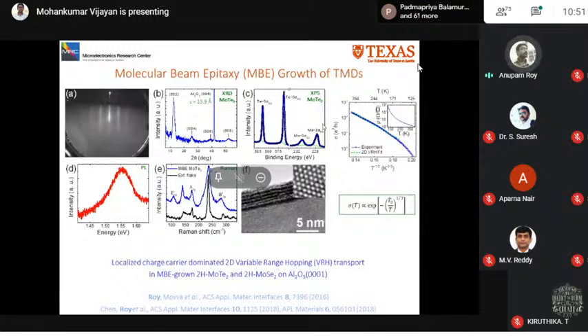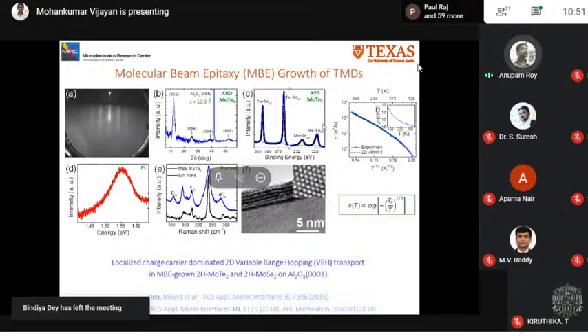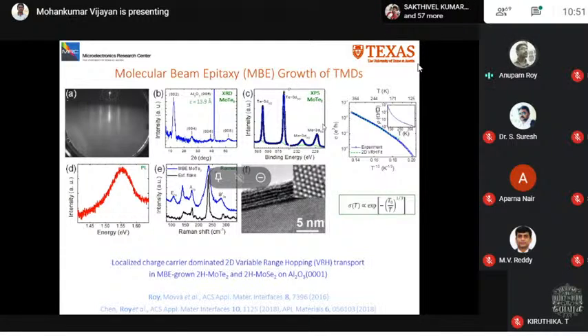And then the characteristic Raman peaks, a band gap of about 1.55 eV in photoluminescence, and good stoichiometry in XPS. So all apparently predicts a high quality large area growth of these materials. However, when we look into the electrical properties, we see that the variable range hopping mechanism is dominating the conduction, indicating that there are several defects in the grown film, and it is proved through transmission electron microscopy, where you can see that there are lots of defects and dislocations present.